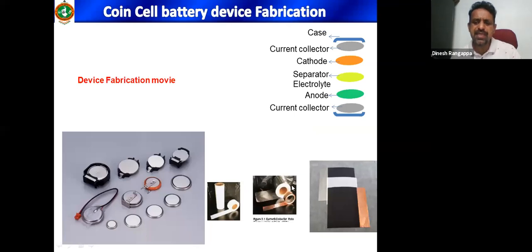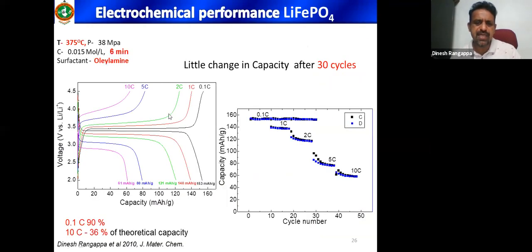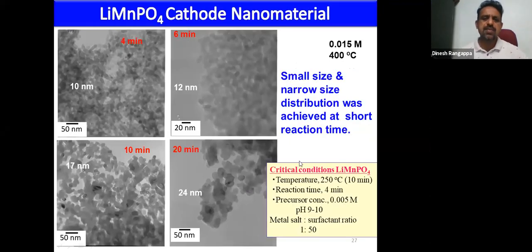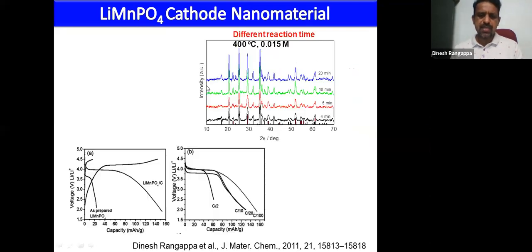Then after fabrication of the electrode, we studied the charge-discharge performance of lithium iron phosphate, and it shows about 90% of theoretical capacity was achieved, with very good cyclic performance and high rate capability up to 10C. Similarly, lithium manganese phosphate electrode material was developed, and the pure crystal structure was confirmed. You can see the manganese phosphate cathode material also gives about 150 capacity at different rates.